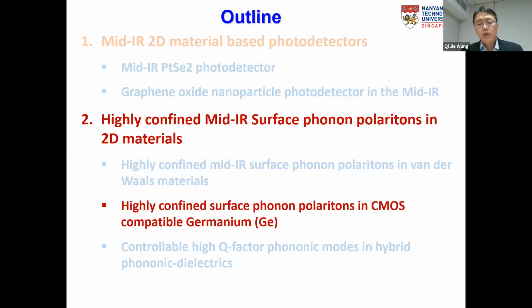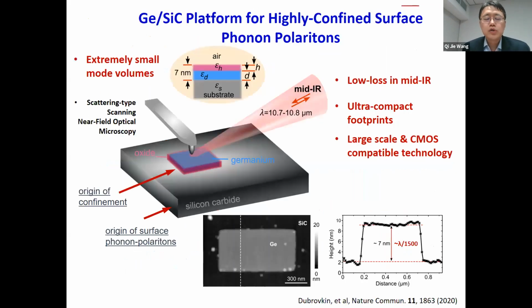So, and then the next, we explore using CMOS compatible germanium material, because graphene is still not really considered a CMOS compatible material, while germanium has extremely low loss in the mid-IR. It has a relatively large refractive index, and therefore can provide a compact footprint. And more importantly, it is a purely CMOS compatible material, and therefore allows us to achieve mass production of such germanium-based devices. Okay, so that's the reason we explore changing the top contact layer, the dielectric layer, to be germanium.